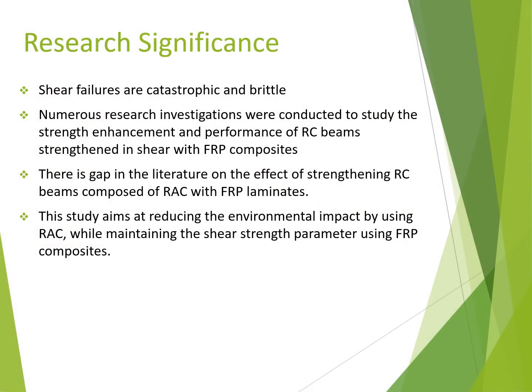Moving on to the research significance. In general, shear failures are catastrophic and brittle. Therefore, the use of FRP materials could be essential to improve the shear capacity of the beams. Numerous research studies were conducted to study the strength enhancement and performance of reinforced concrete beams strengthened in shear with FRP. However, there is a gap in the literature on the effect of strengthening RC beams composed of recycled aggregates with FRP laminates. Therefore, the study aims at reducing the environmental impact by using recycled aggregate concrete while maintaining the shear strength parameter using FRP composites.